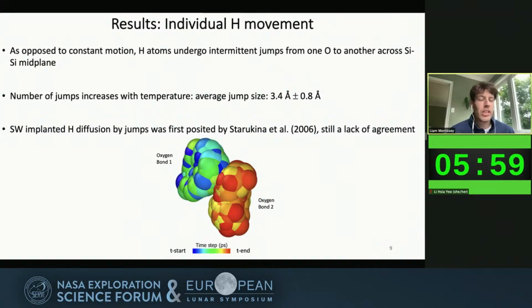As opposed to the constant motion that you'd expect to see in a diffusion system, we actually noticed that the H atoms instead underwent intermittent jumps from one O to another across the Si-Si midplane. We also noted that the number of these jumps increased with temperature, and we found an average jump size of about 3.4 angstroms.